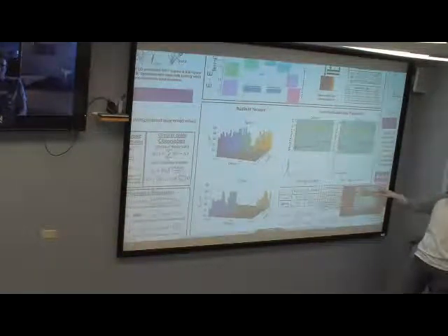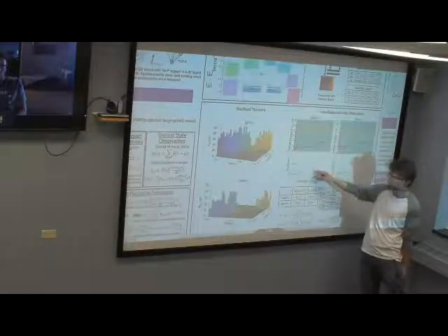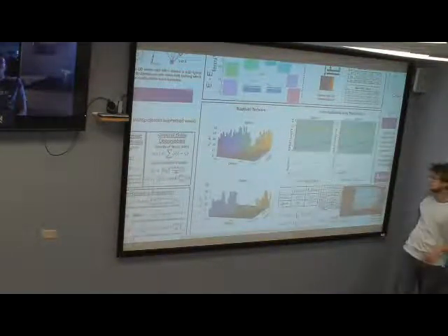And you can see that there's quite a wide variation in the relaxation time between those two. So this is on a log plot. For the spin alpha component, it relaxes to the band gap in under a picosecond, whereas for the spin orbit computed relaxation, it's above 10 picoseconds, edging up towards 100. So it's almost a 2 to 3 orders of magnitude difference in the hole relaxation, just based on computing with a different basis.